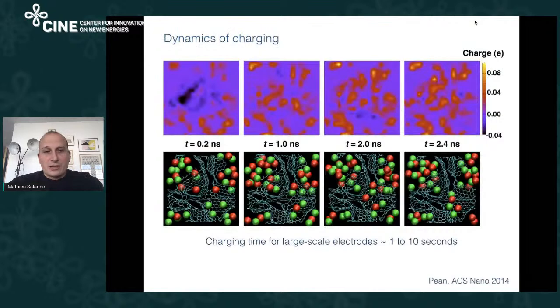Then we also looked at the dynamics of this effect, because an important question is, of course, due to confinement, you can expect the dynamics to become very sluggish. And in fact, what happens here also is that the disorder of the structure is playing a role. So at the top here, you have maps showing the charge on the carbon atoms depending on the time of the simulation. At t equals 0, the potential was null, but then we applied the potential. And you see that some regions start to be charged very quickly, and some others are charged only after several nanoseconds, which is a long time scale when we are looking at molecule movement.